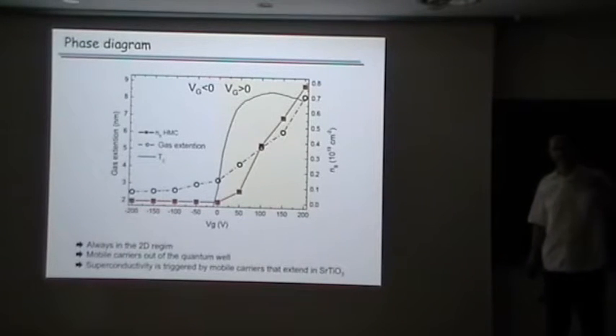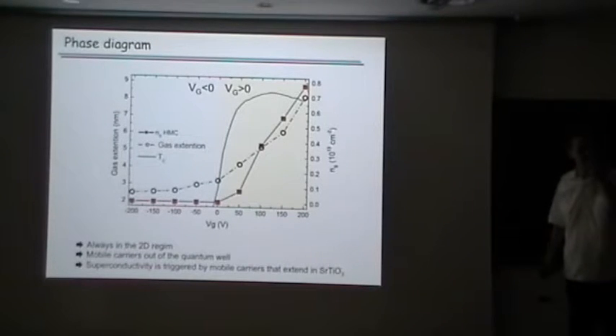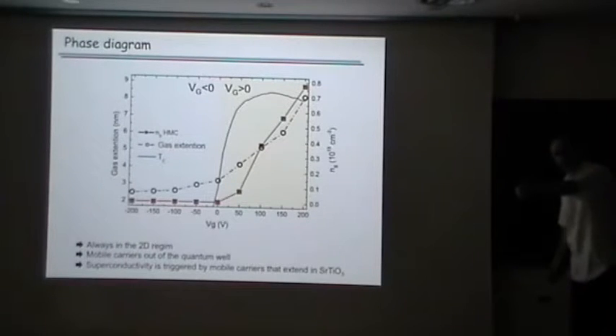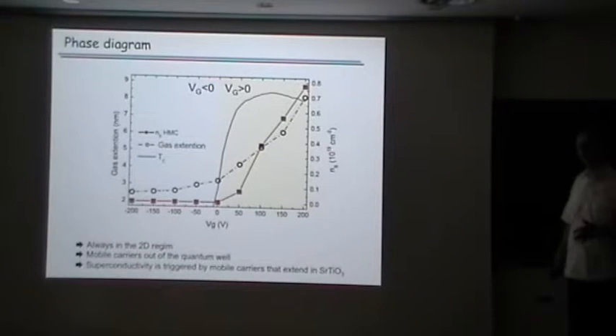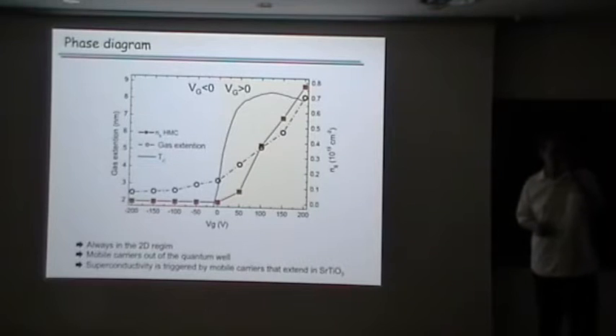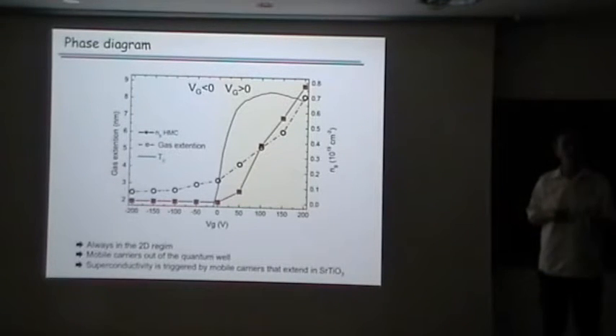So maybe it's a naive picture, but the feeling we have is that when you put electrons in the system, electrostatically you put them further away from the interface, and they are highly mobile because they are not strictly 2D like the ones within the potential well. So our picture is that we don't have multiple carriers because we have multiple bands, but because we have carriers confined in the well and carriers away from the well.